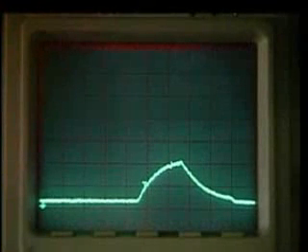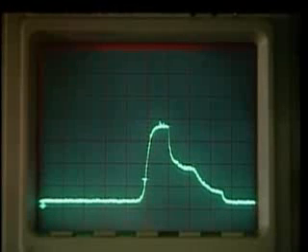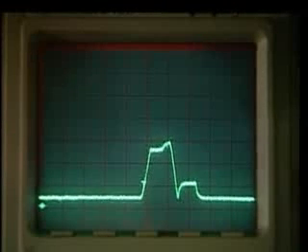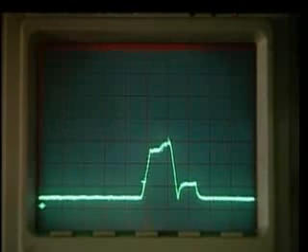Waveform control technology controls every aspect of the output waveform. First, a high-speed control delivers the ideal instantaneous welding output. Each weld is made up of individual droplets of weld metal, and the high-speed control regulates the development and transfer of each droplet. The second control, the slower-speed control, adapts the wave shape to maintain the proper arc length.